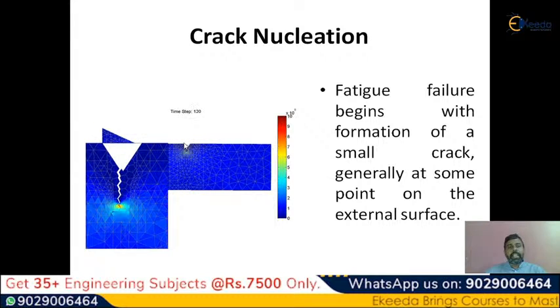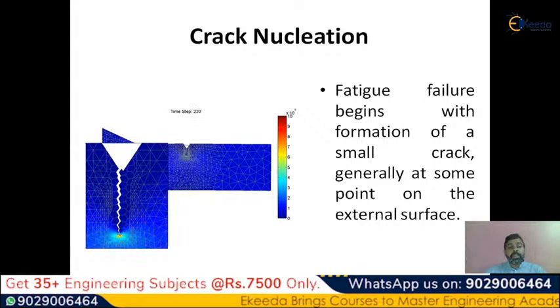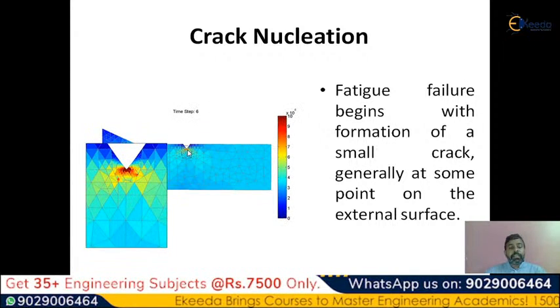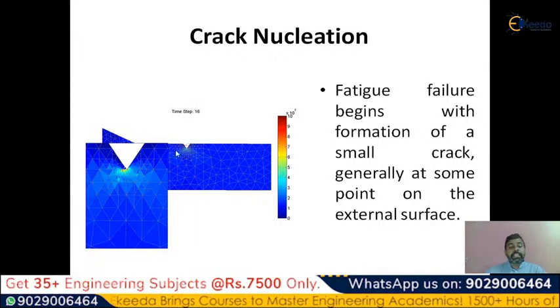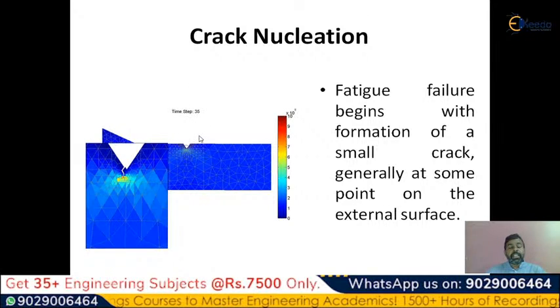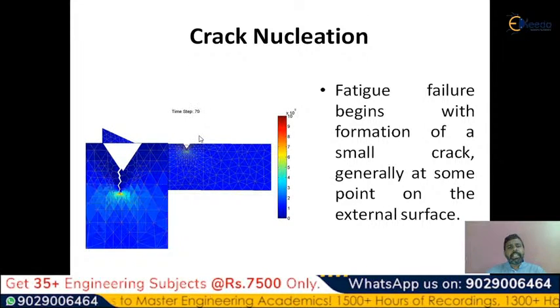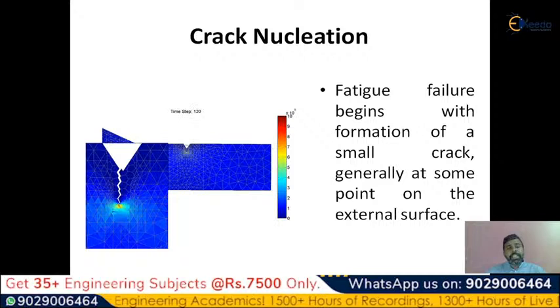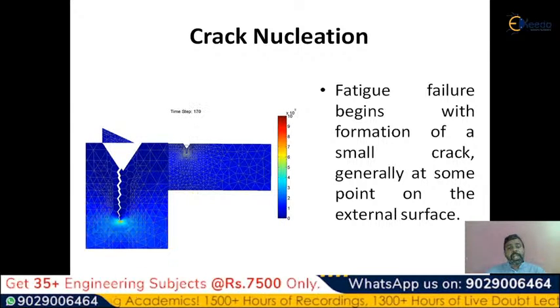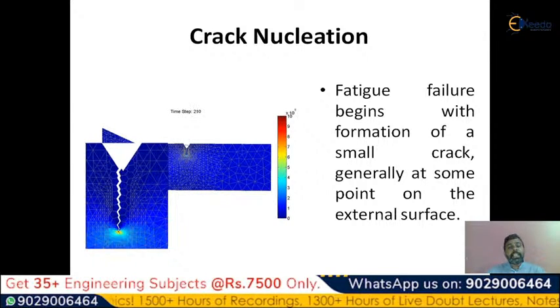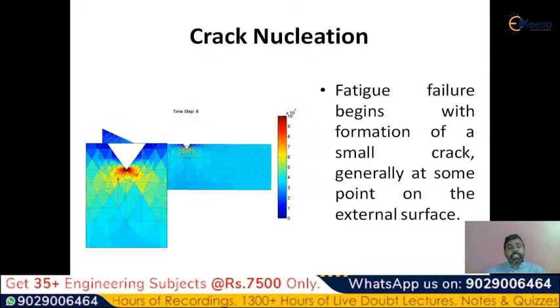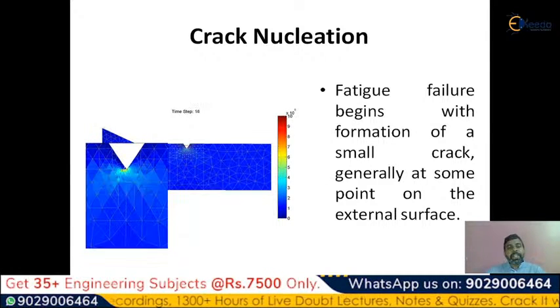In general, the crack nucleation will start at the surface. In 90% of the cases this will happen. In 90% of the materials, the crack will nucleate at the surfaces. This is the first stage of the crack after repeated loads.